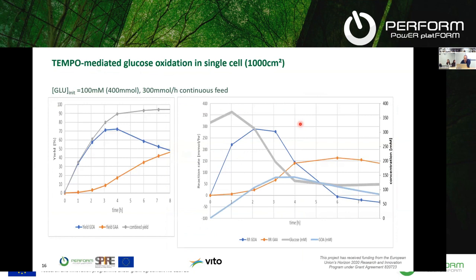So in this case, this is the graph, actually the results of the continuous feed experiment, where we used the cell in a continuous mode. This is just by adding glucose in a concentrated way at a rate of 300 millimoles per hour. And as you can see, the total yield here is quite large, but it consists of a yield of around 40 to 50% of gluconic acid and also glucaric acid.